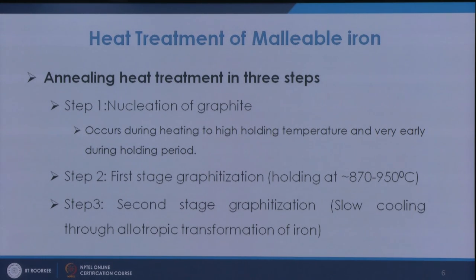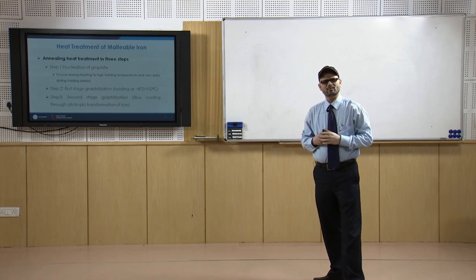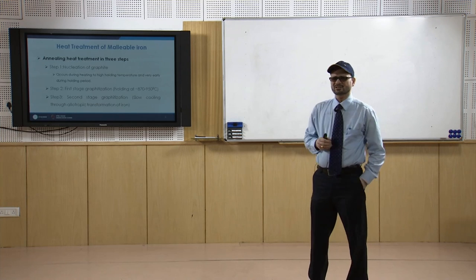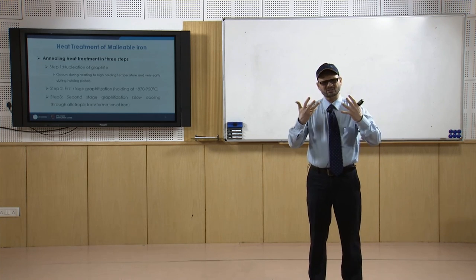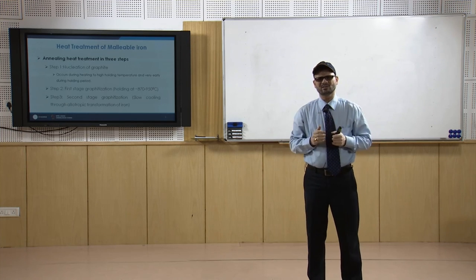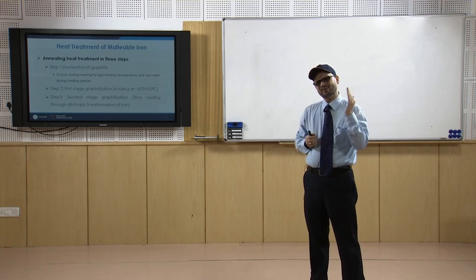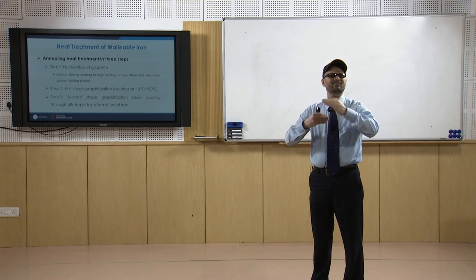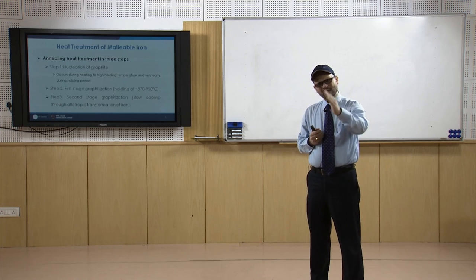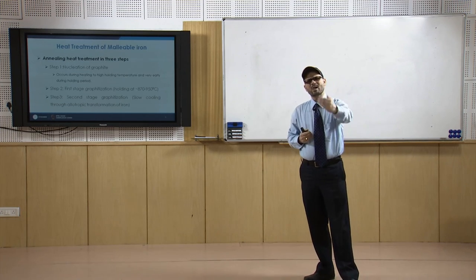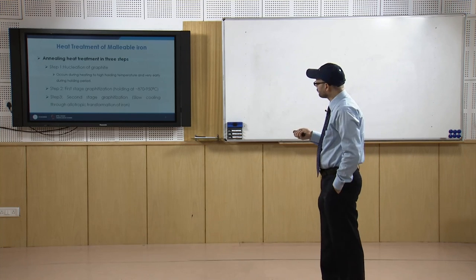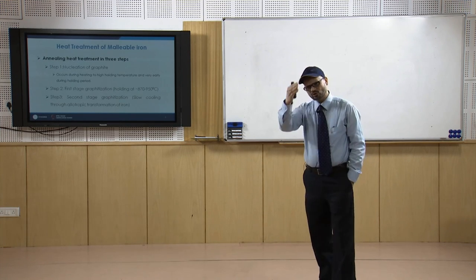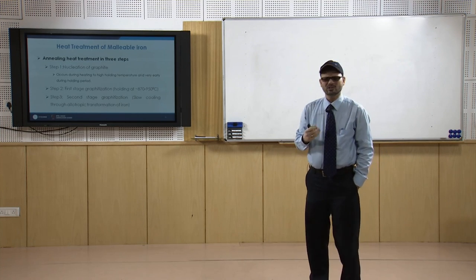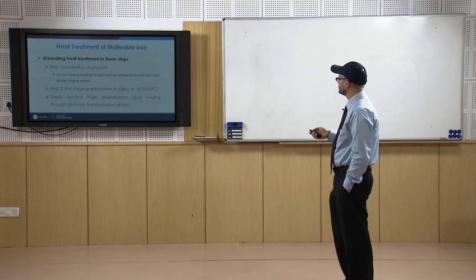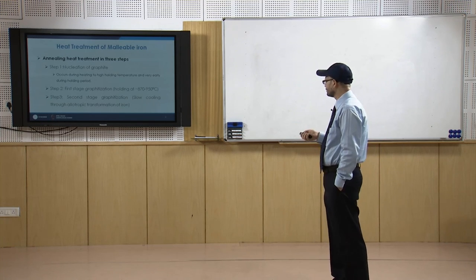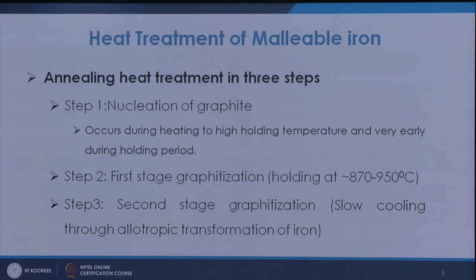When we cool slowly through the allotropic transformation range, the kind of matrix that will be formed is governed during that process. All the carbon is further removed and you get a ferritic type of matrix. That completely ferritic matrix formation takes place during the second stage of graphitization, during the slow cooling through the allotropic transformation range. That is known as second stage graphitization, or SSG. The earlier one is known as first stage graphitization, or FSG.